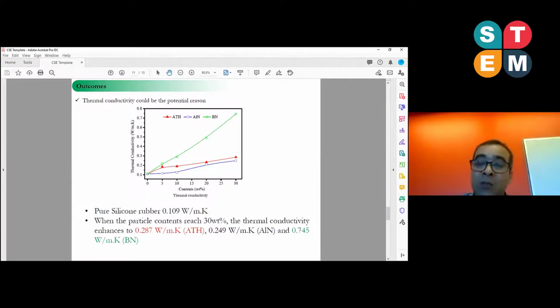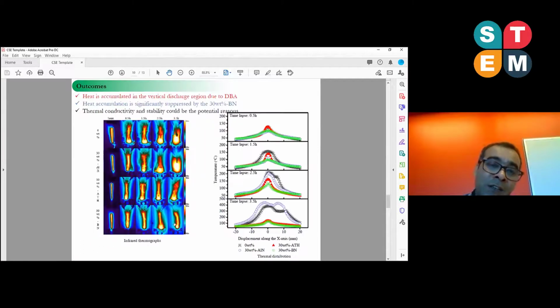So that could be one reason, because the thermal conductivity is higher in the insulation. During the tracking and erosion, during the heat accumulation, because the thermal conductivity is higher, it can conduct heat very easily into the ambient and can reduce the temperature in the middle of the sample. So that makes a lot of sense.